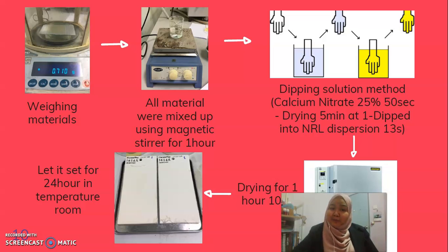unglazed ceramic plate, which I will dip in calcium nitrate 25% for 50 seconds and dry in the oven for 5 minutes, and then dip into the dispersion for 13 seconds. After that I will dry it in the oven for 1 hour at 100 degrees C. Then I will let it set for 24 hours at room temperature.